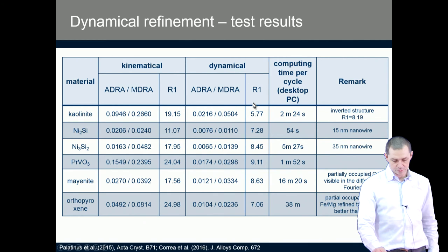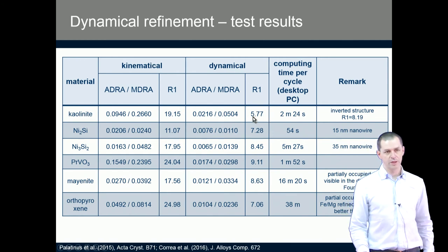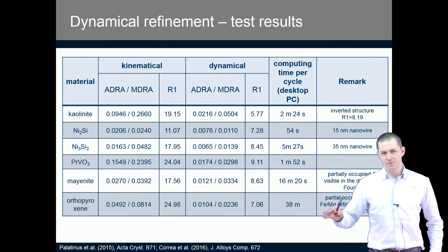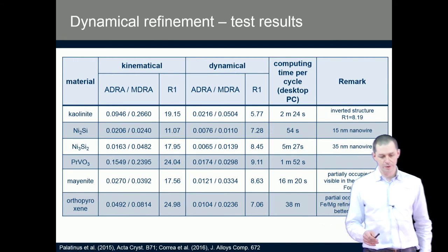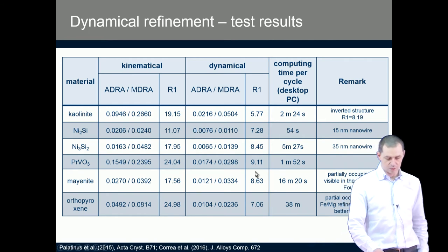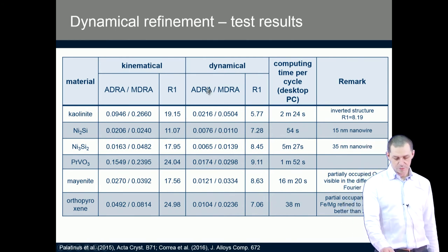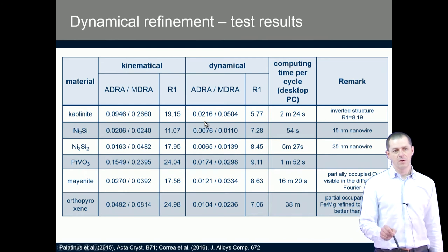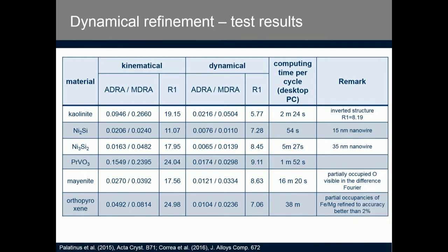And the refinement R values with dynamical refinement are all below 10%. They are not quite at the level of 3-4% that we are obtaining with X-ray diffraction, but they are already in what I would say acceptable range of R values. What is more important is these numbers, which show the average discrepancy or displacement to reference atoms, so the average error of the structure determination compared to the reference X-ray structure. And here we are getting numbers that are around 0.01 to 0.02 angstroms. So that's about the accuracy that we can reach if we have good quality electron diffraction data and if we